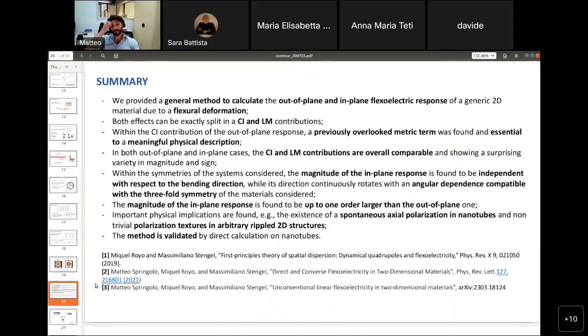So we can conclude by saying that we managed to develop and provide a general method to calculate the out-of-plane and in-plane flexoelectric response of a generic two-dimensional material, and that we found that both of them can be split into a purely clamped-ion and a lattice-mediated contribution. Particularly in the out-of-plane response, and in particular in the clamped-ion response, we found a previously overlooked metric term that is actually essential to a meaningful physical description.